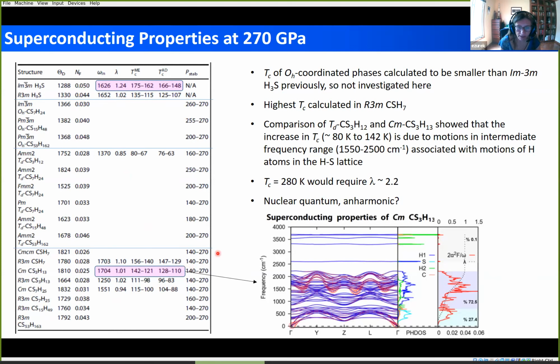But what I would like to point out is that even though we have gone one step further than taking a look at the virtual crystal approximation, what we have not considered is the nuclear quantum effects, which could serve to smear out that proton between the carbon and the sulfur, thereby potentially raising the density of states at the Fermi level. So that's not considered in our calculations, nor have we looked at the anharmonic effects.